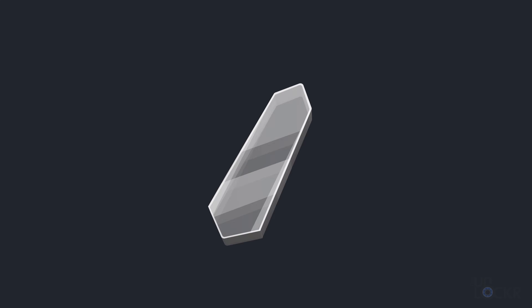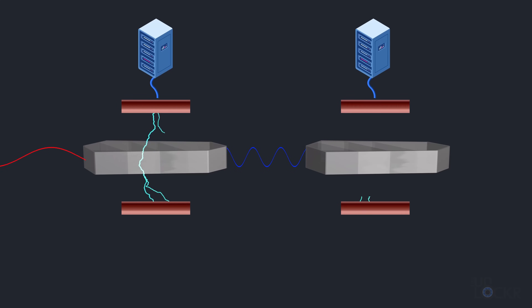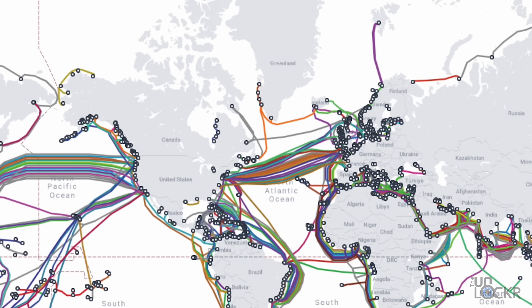The reason this material has been so prized over decades is because of its unique properties, including a high refractive index, a high degree of transparency, and a high second-order non-linearity. But the really unique feature that solidified its use in the world of fiber optics and photonics was that it exhibits the Pockels effect. This means the material naturally responds to an electrical field in a directly proportionate way. So if you have a beam of light going through the crystal and you put electrodes on either side and pass electricity through it, the light beam itself changes in direct correlation. This makes lithium niobate a natural converter for electrical into photonic or optic signals, and it was the material used to help create the global fiber optics network — the backbone of the internet — created in the 90s.